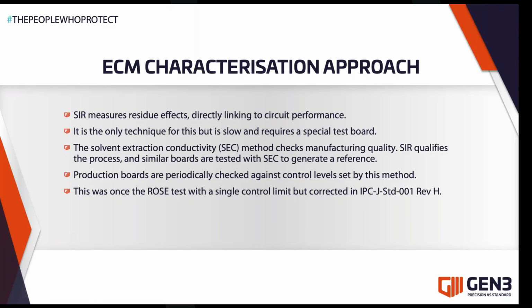SIR qualifies the process, and similar boards are then tested with SEC to generate a reference. Production boards are generally periodically checked against control levels set by this method. This was, of course, known in the industry as the Rose test with a single control limit, but it's since been corrected in IPC J-STD-001 Rev H, with the removal of the Rose 1.56 micrograms of sodium chloride. So Chris will quickly go through the principles of this.